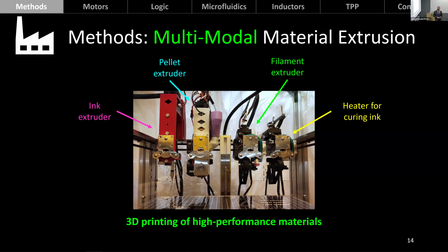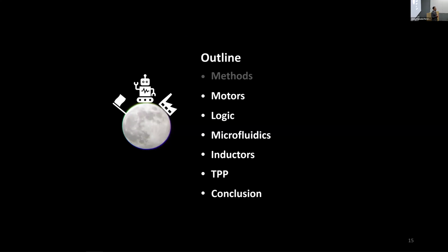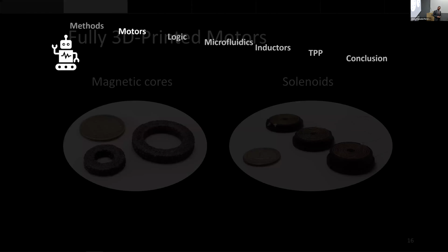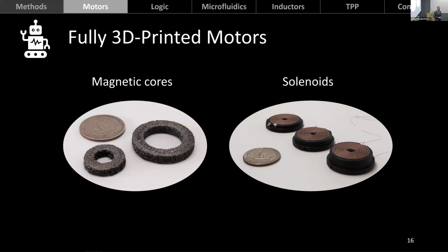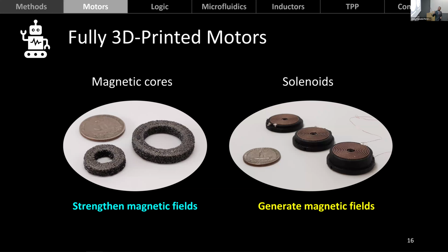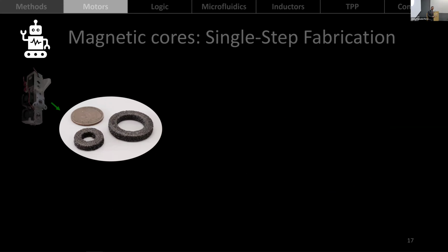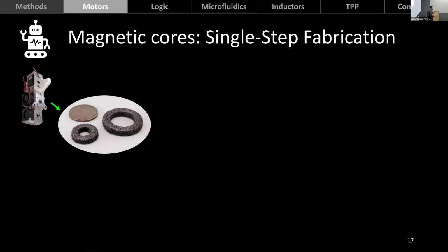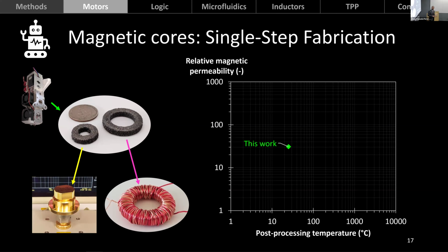So what do we do with this? Well, that's what I'm going to talk about now. The different applications, the different devices that we were able to fabricate with this technology, starting with motors. So motors typically comprise magnetic cores and solenoids, and they can also have permanent magnets. I'll mention that later. Magnetic cores are meant to strengthen magnetic fields, while solenoids are the ones responsible for generating those magnetic fields. And I'm going to start looking into the magnetic cores. So by introducing the pellet extruder, we became able to fabricate these cores from a higher performing material. And we characterized them in several ways and found that we are able to reach this relative permeability of about 30.